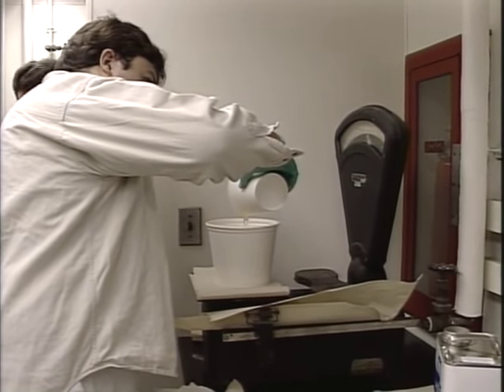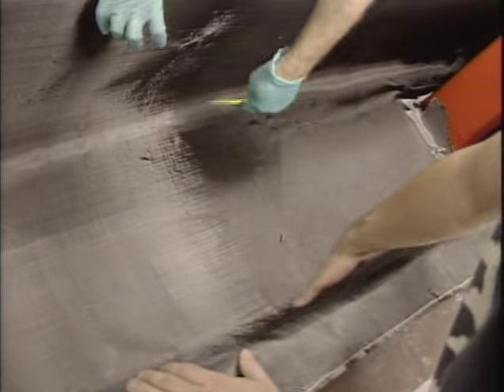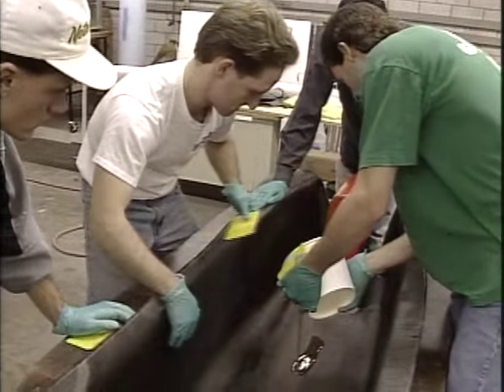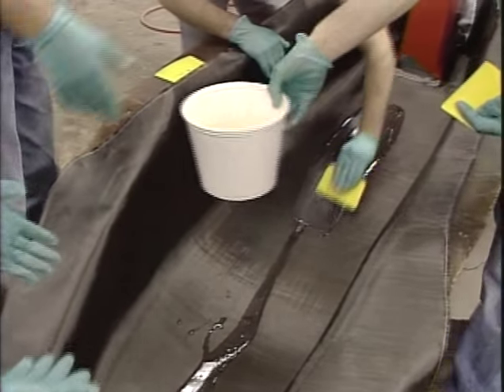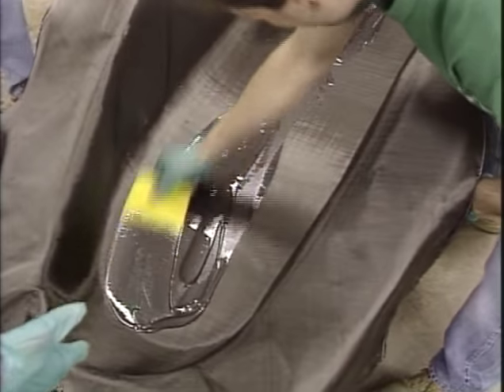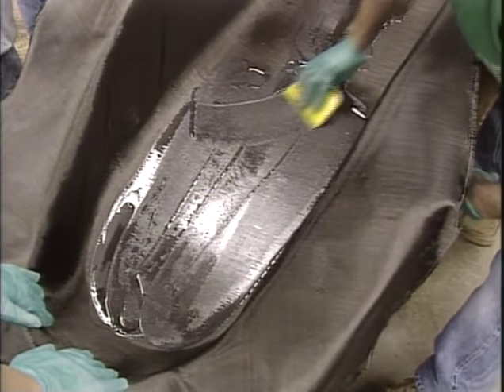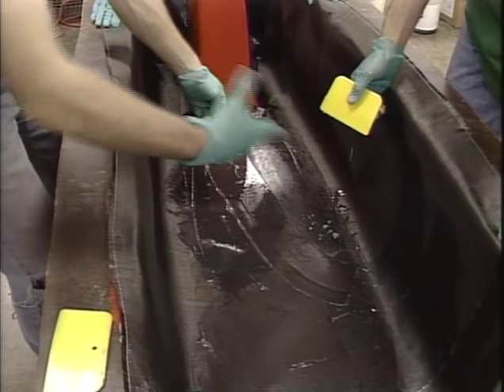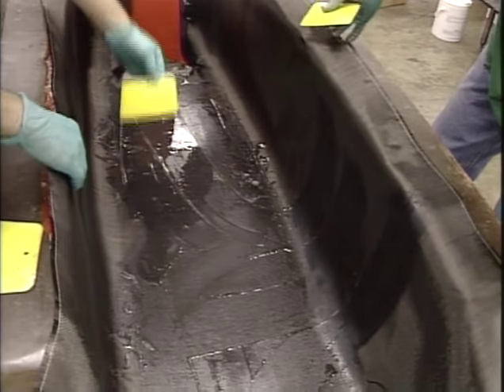While we were placing the fabric, another student was mixing the epoxy. As soon as the epoxy was mixed, we had to become aware of the time. We knew that the resin would want to pull to the bottom. I had decided not to apply a surface coat and instead allowed the resin to saturate the graphite from the top. We would be vacuum bagging out the excess resin and believed we could adequately saturate this surface layer without a surface coat. We were concerned about not getting enough resin into this layer or trapping air pockets.